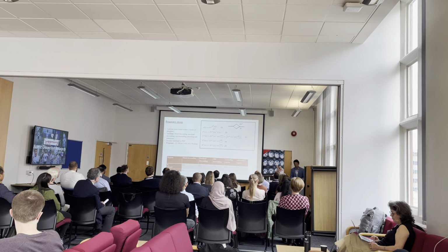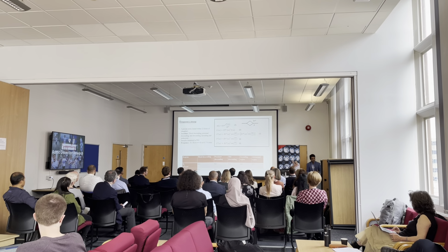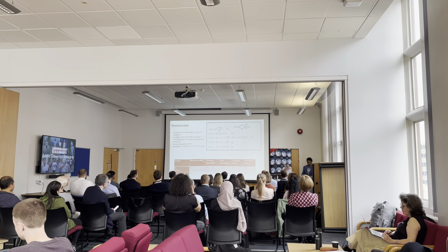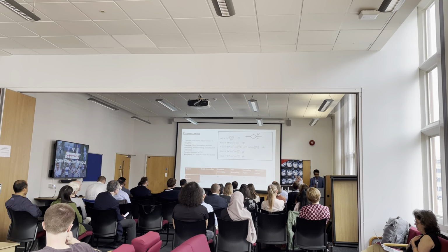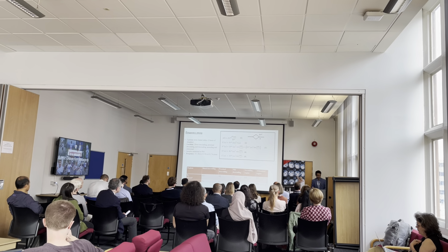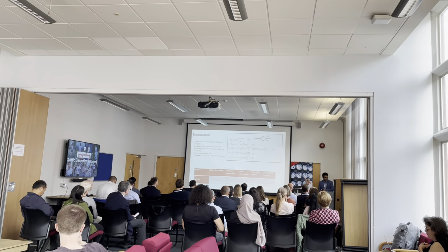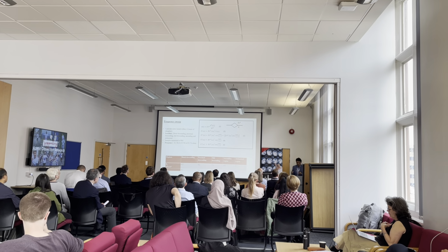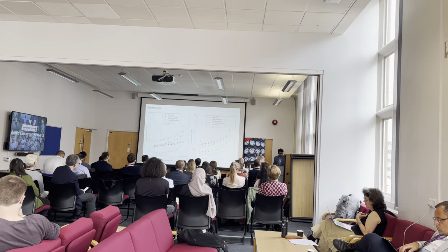Alpha is the order of the fraction, which tells us how dependent these samples are upon the frequency. The higher the value of alpha, for example in the ascending region, the more drastically the storage modulus increases as a function of frequency. In the proximal descending and the distal descending region, it increases less. So we were able to quantify these parameters across different regions of the aorta.